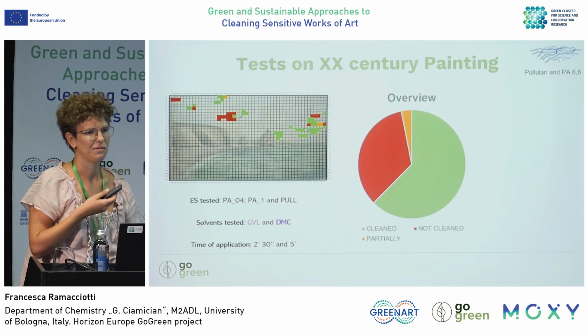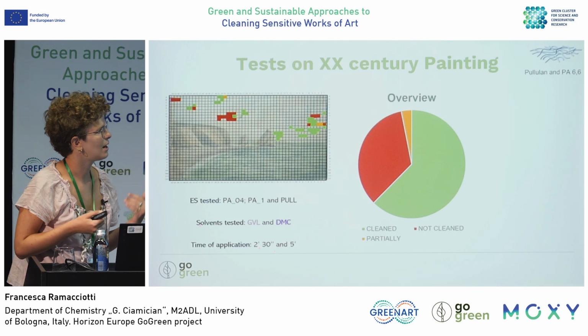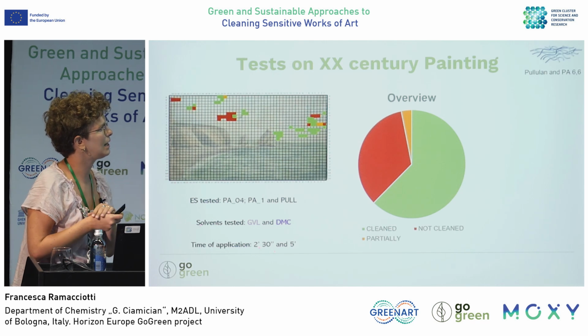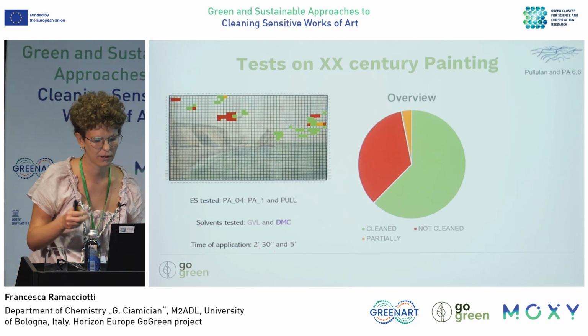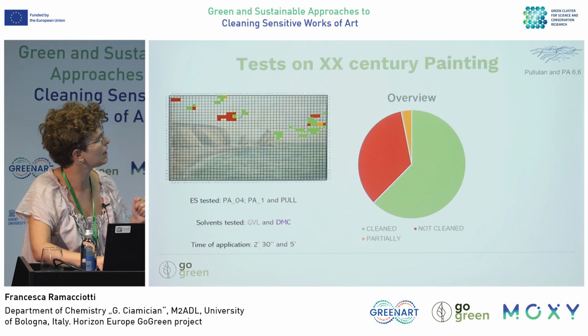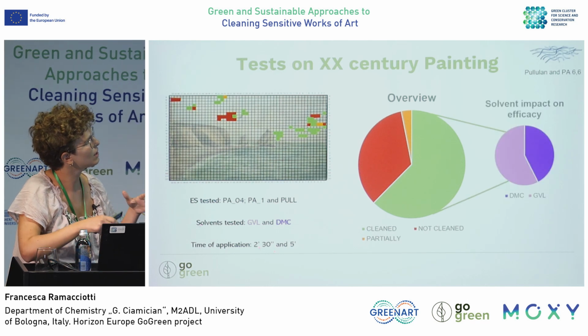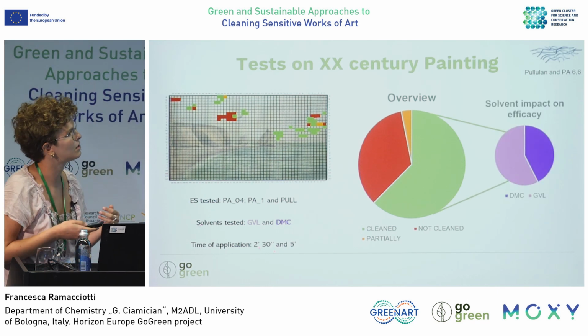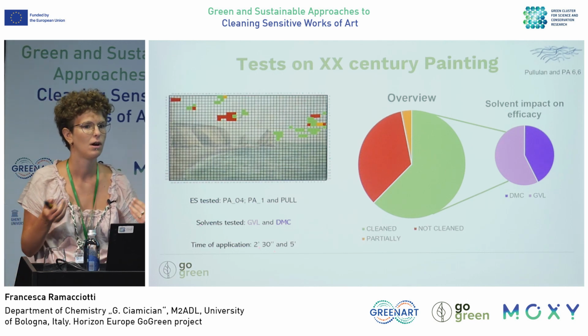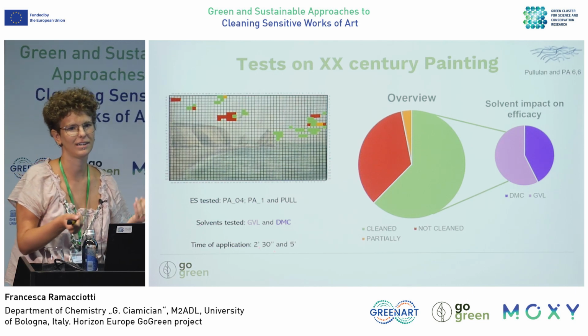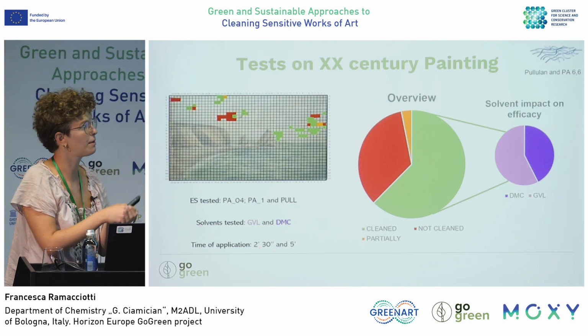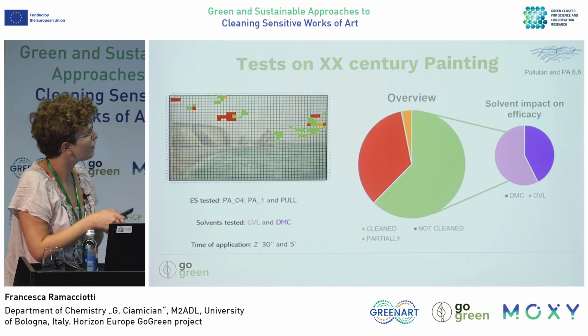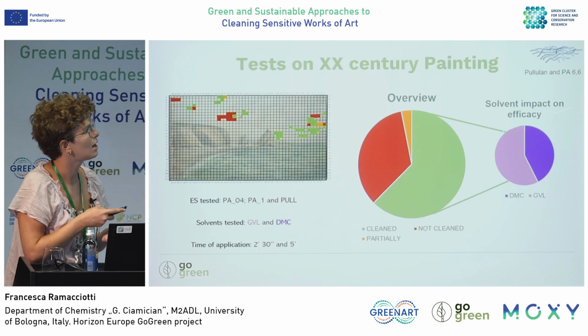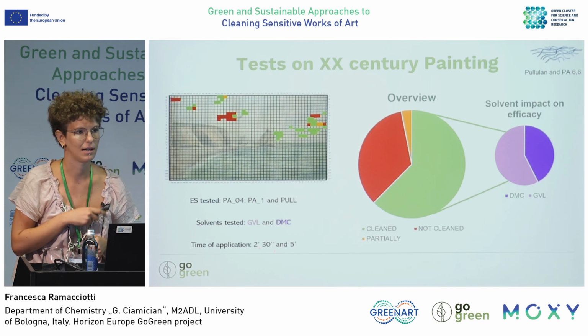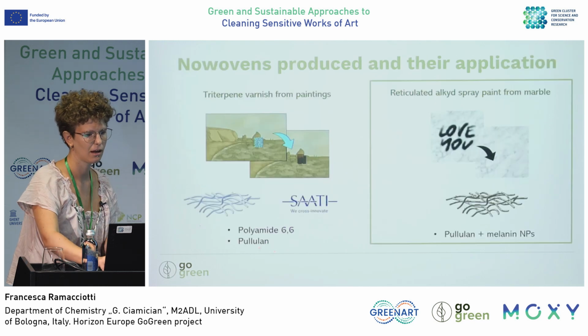As you can see, we had a good success, so we had more than half of the tests with good cleaning performances, but what really impacted our cleaning efficacy was not the kind of tissue, but actually the solvent that we selected. So this varnish was way older than the one on our mock-up, so more polar, and that's why gamma valerolactone led to better results than dimethyl carbonate.